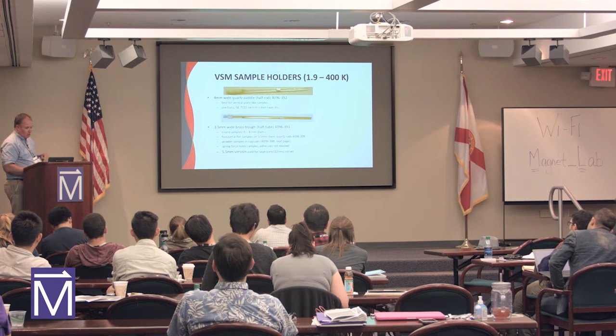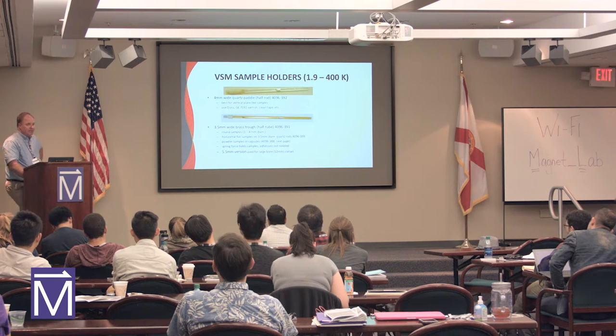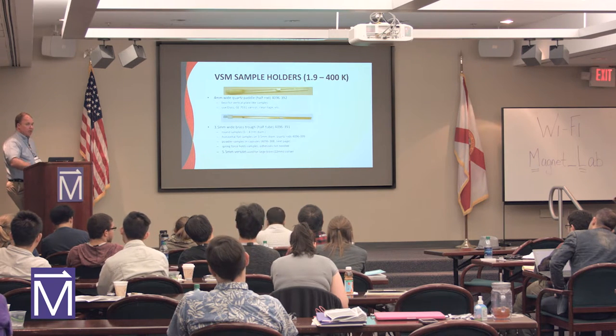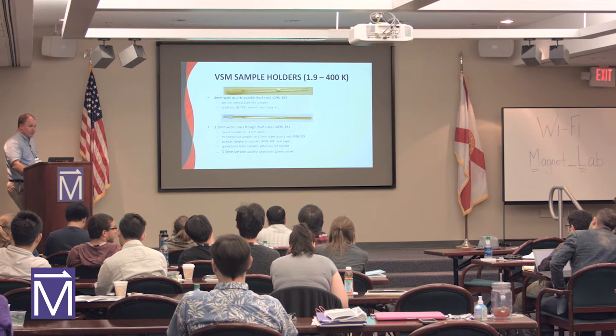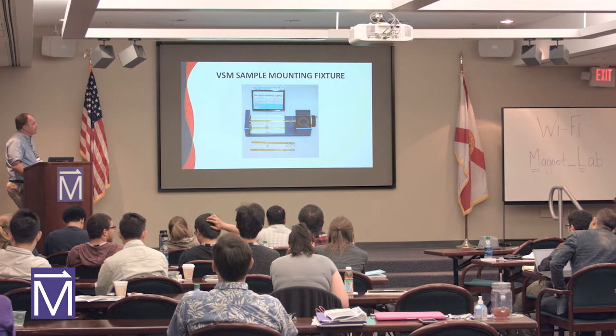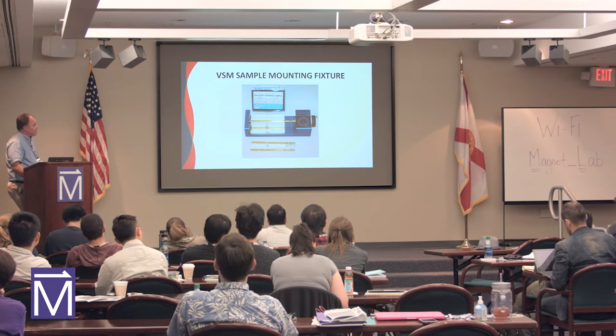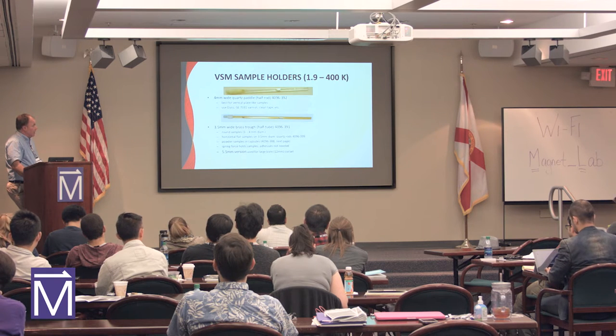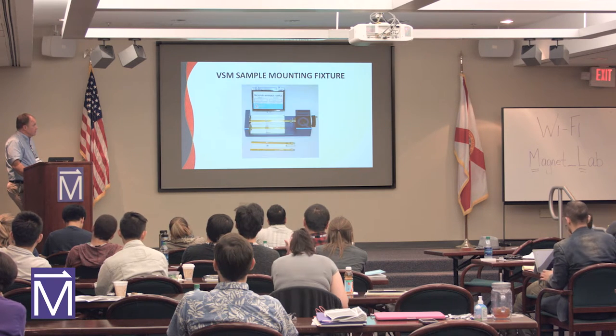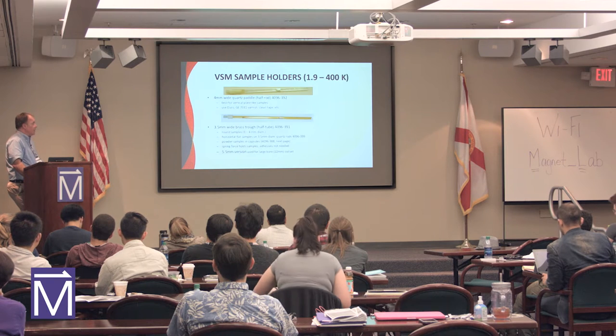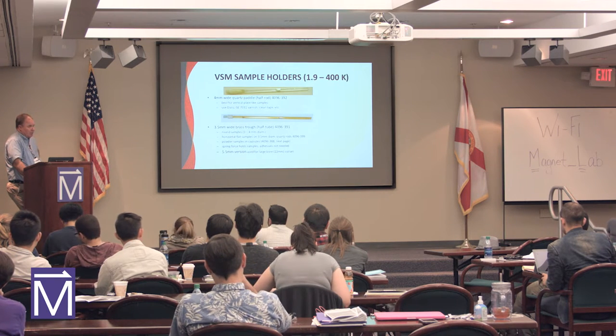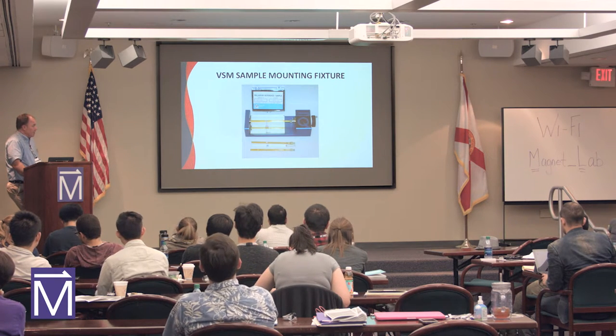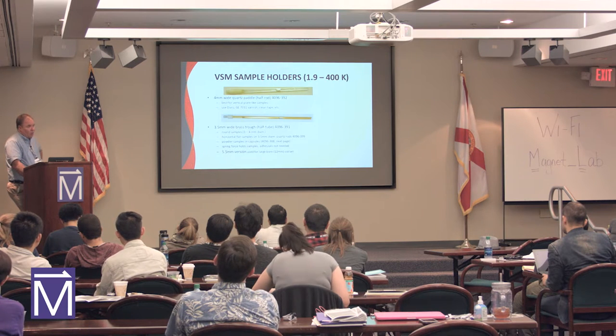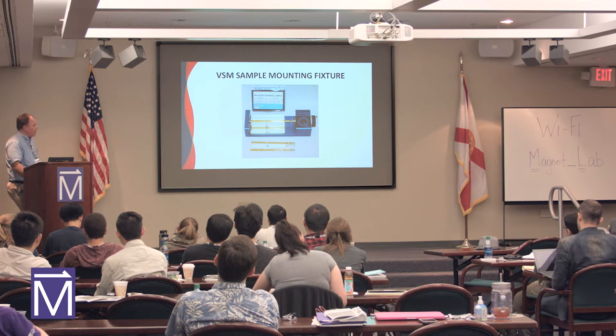And then we've got a little larger version of the same brass tube that fits into the large coil set. So we've got a small and a large, 6 millimeter and a 12 millimeter diameter coil set, so the pickup coil diameter. We've got a little mounting jig. On these two holders, you know where the sample location is in the center. Especially on the quartz paddle, so you can figure out where your center is.